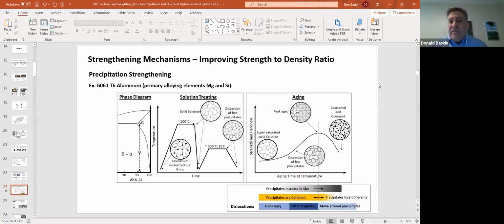Another very potent method for improving strength to density is precipitation hardening. When you add different materials to the base material, like an alloying element, if the thermodynamics and the size are such that they don't form a solid solution, either substitutional or interstitial, a lot of times they'll form what are called precipitates, which are sometimes little oxide particles only a couple nanometers or a couple microns wide. These little particles are very effective at making it more difficult for a dislocation to move through the lattice of the material. The energy to move that dislocation through the lattice increases dramatically in some cases when you have precipitation strengthening.